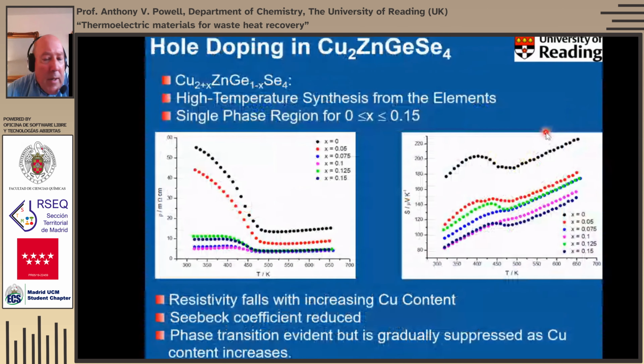So I realize I'm probably getting close to the end of time, so I'll go through some of the remaining material at a reasonable speed. We've done some hole doping on that end member phase. We get a single phase region up to about x of 0.15. So in other words, what we're doing is replacing germanium 4+ with some copper. That requires the copper to be oxidized from copper 1+ to copper 2+, and consequently we introduce some holes into our structure. What we see then as we increase that hole concentration is that the resistivity falls. And also, of course, there's a corresponding fall in the Seebeck. And although the phase transition is still evident, you can see that it's gradually being suppressed.